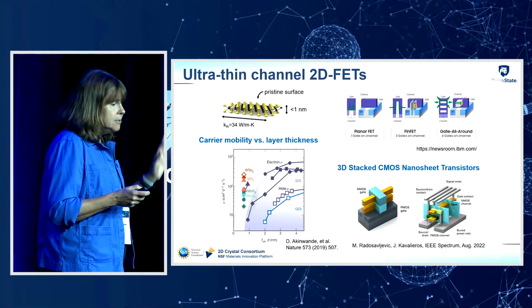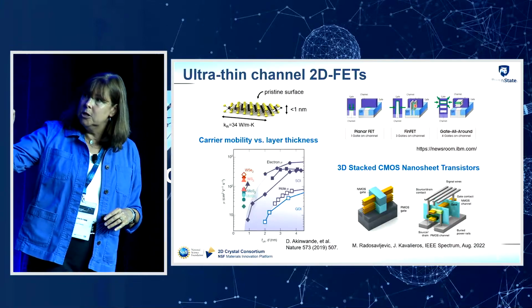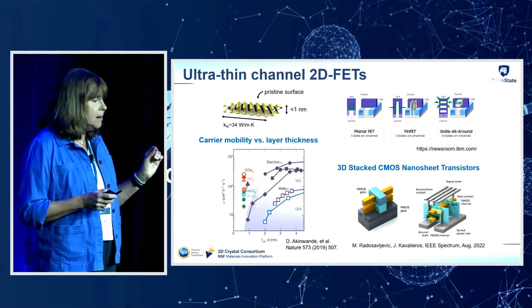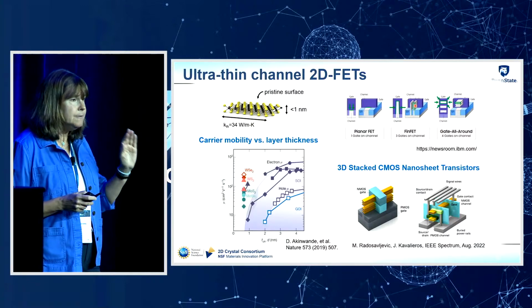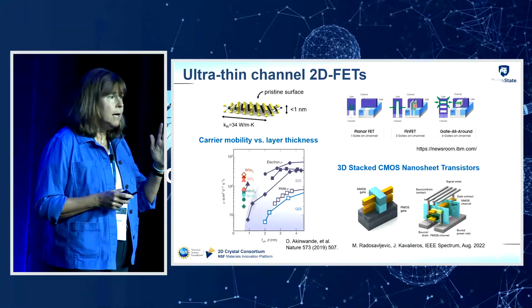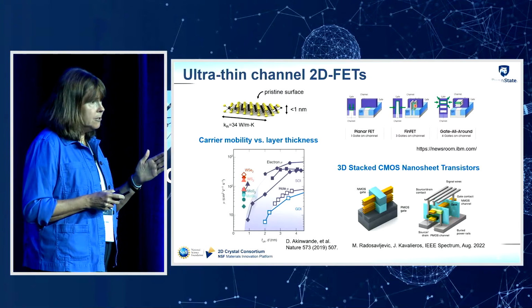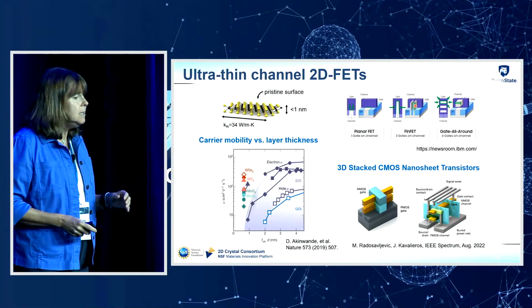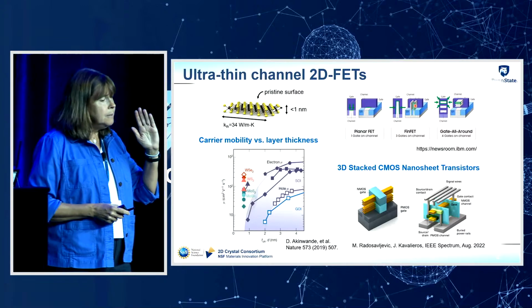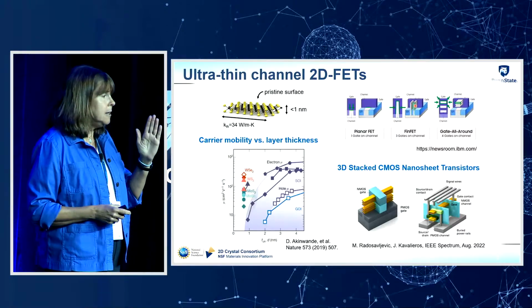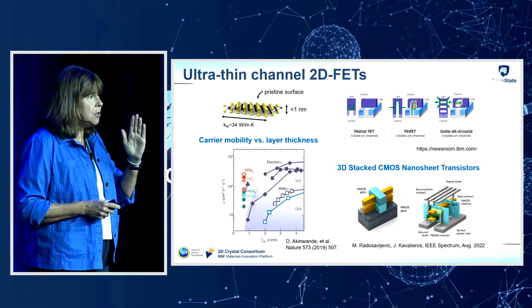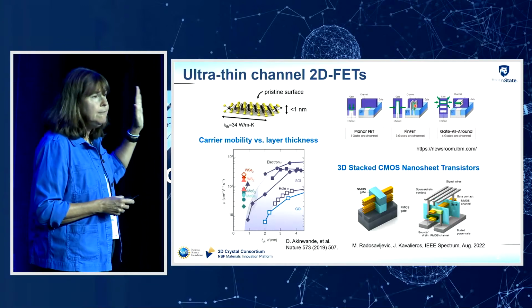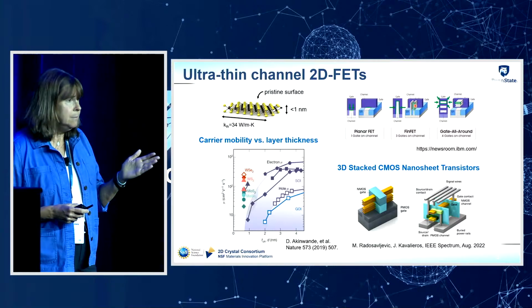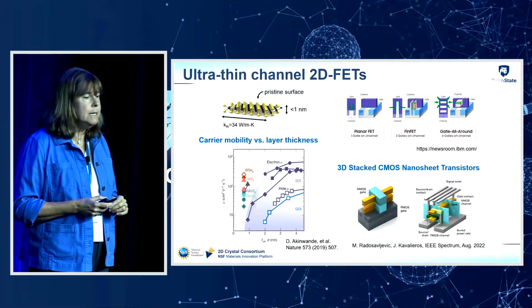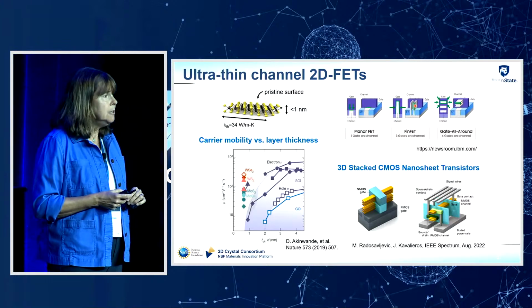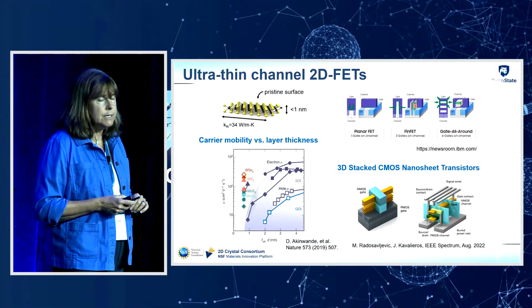The reason for this is shown in the figure at the lower left. This again is comparing the carrier mobility of silicon to that of transition metal dichalcogenide monolayers. You can see the mobility of silicon is dropping off, but the mobility, or the transport properties, of our TMD monolayers are quite good even at thicknesses below 1 nanometer. So that sparked a lot of excitement in incorporating these materials in future generation integrated circuits.